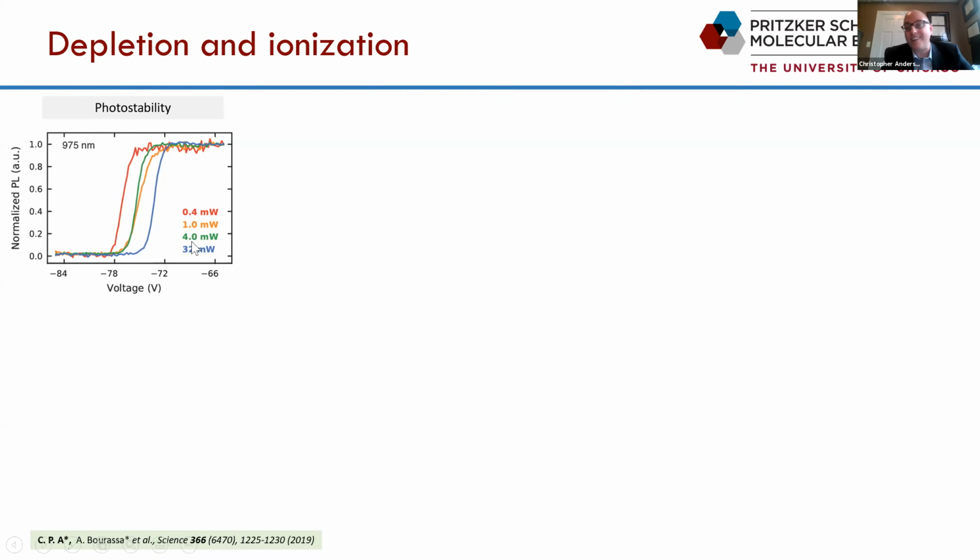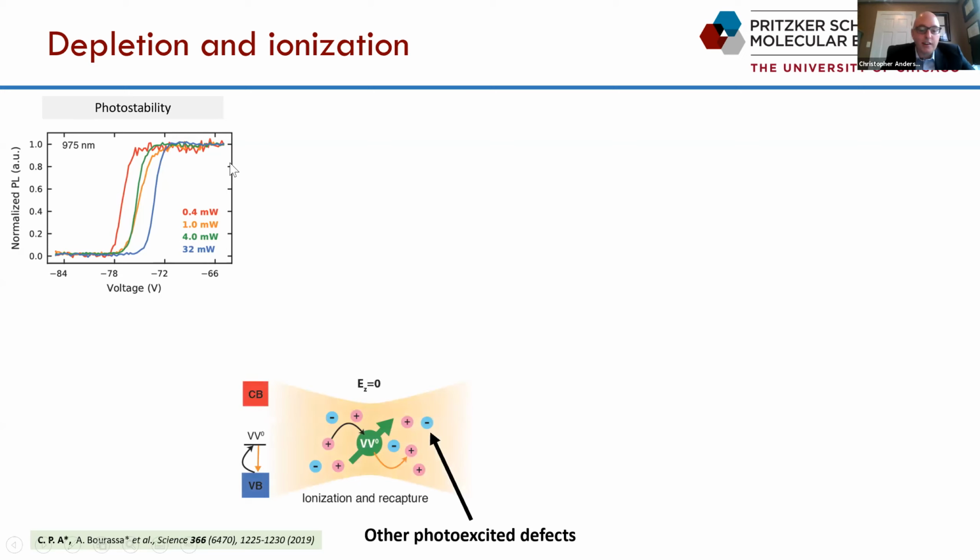It stops emitting light. The way that we can understand this essentially is that under photoexcitation, our divacancy defect has a chance of photoionizing by accident. However, under zero applied field, there's a bath of surrounding photoexcited free carriers, in this case probably a little bit hole rich, such that there's always a free carrier available to bring us back into the light emitting, bright, neutral state.